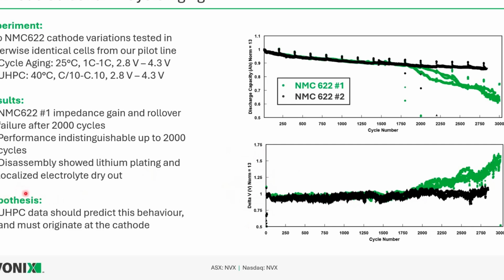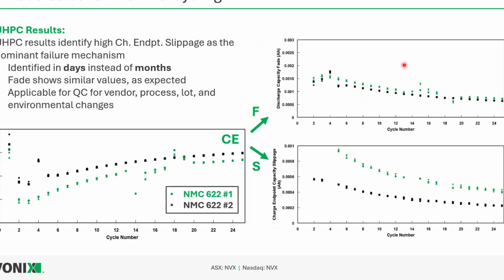So the hypothesis here is that UHPC data should be able to predict this behavior faster because we know something should be happening that's strictly related to reactions happening at the cathode. It's the only thing different between these cells. They're made on the same day, made with the exact same anode coating, exact same electrolyte batch, etc. You can see they perform very similarly.